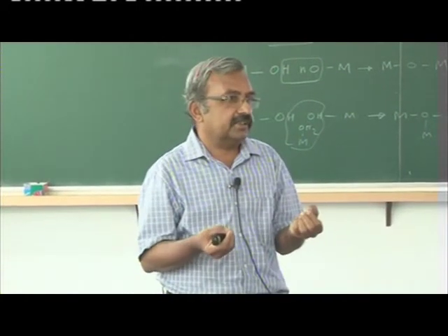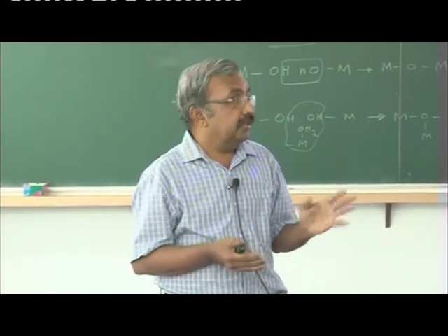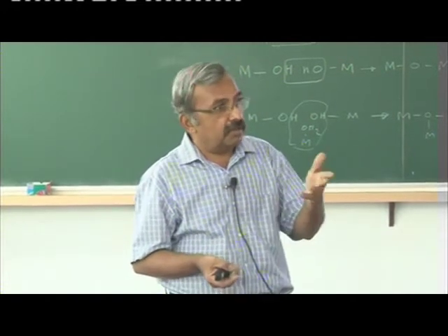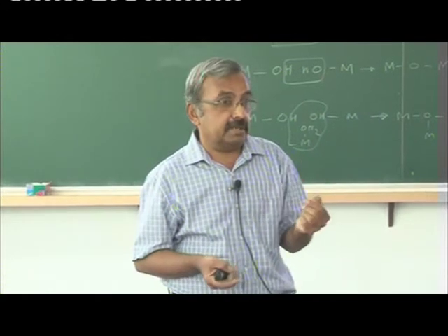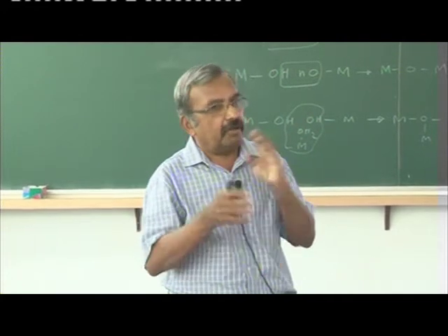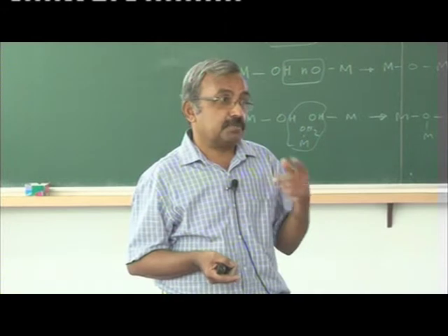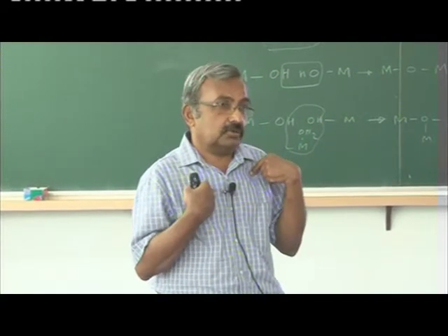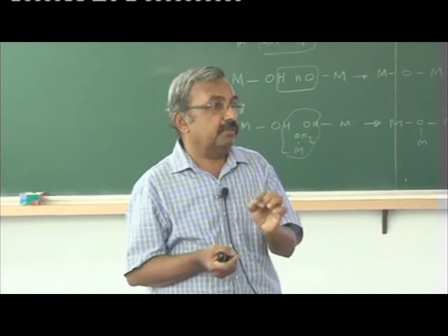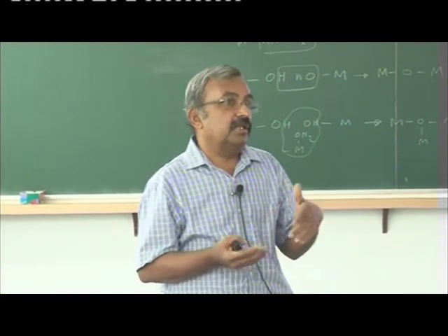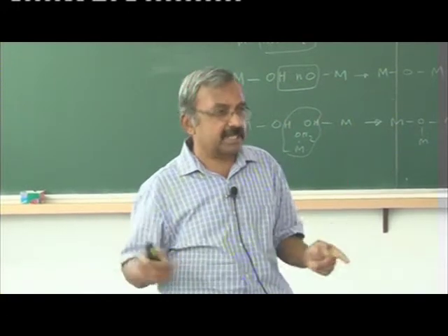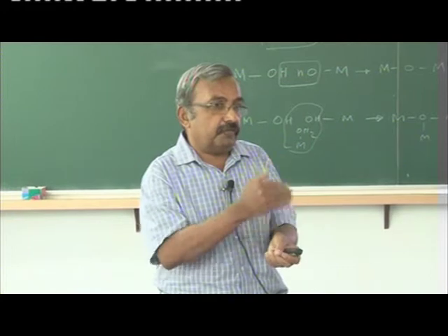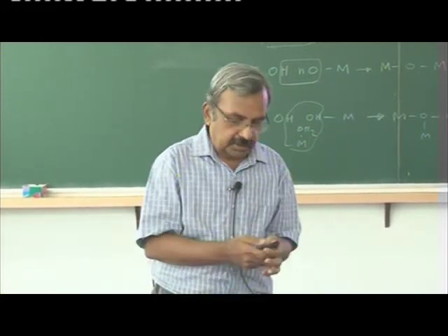Right? So next time when you grow a crystal, most of the time people will use the term recrystallization. In supramolecular chemistry, especially when you are dealing with complex metal organic species, you have to be extremely careful. Not only metal organic chemistry, even in organic chemistry it's a big problem. A good example is benzamide. Benzamide is a crystal which is made by almost every organic lab. But today people realize that benzamide has polymorphs. Depending on the way you crystallize, it's not necessary that you get the same compound. But the way we are taught in the colleges or in the schools, for benzamide you only look at the melting point. Many a time the polymorphs' melting points may not vary. And with NMR and other techniques, you only look at the molecule, you are not looking at the assembly of the molecules. So things can vary, right? So you can say you are able to recrystallize only if your powder diffraction patterns of the compounds at different stages are identical. So I will stop here, and if you want to ask questions, please.